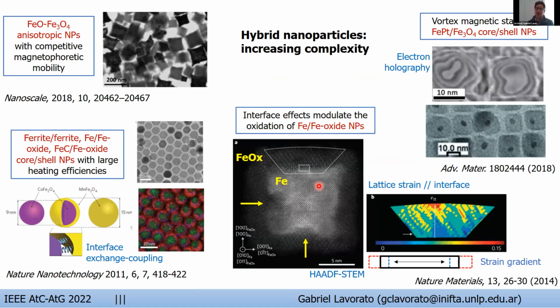We know that metallic iron is oxidized to iron oxide, but it was shown that this chemical reaction is also modulated by the lattice strain produced at the interface between both phases. And this process is size and shape dependent. And in addition, the core shell nanoparticles can stabilize vortex magnetic states, as shown here in the electron holography experiments, that are quite unusual for single-phase particles. So overall, this means that both chemical transformations and magnetic properties can be strongly modulated by interface effects and deserve our attention.